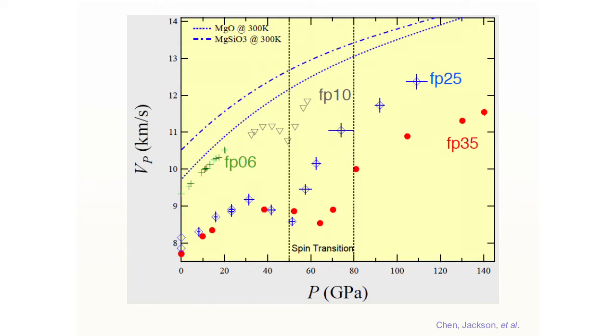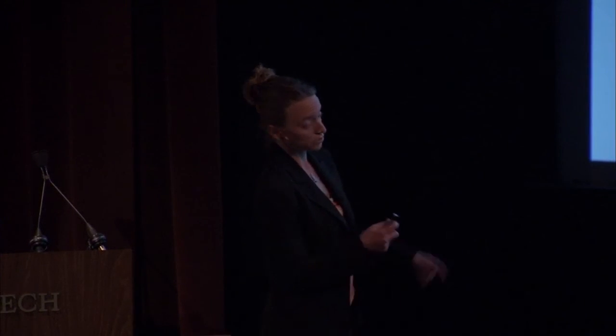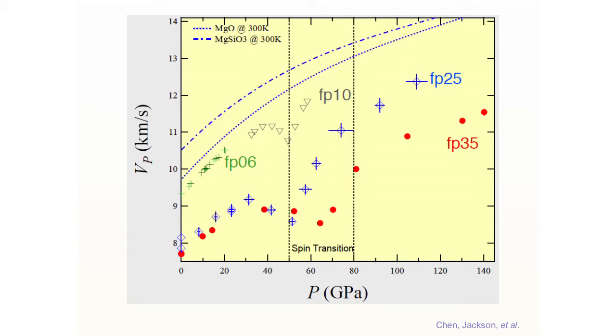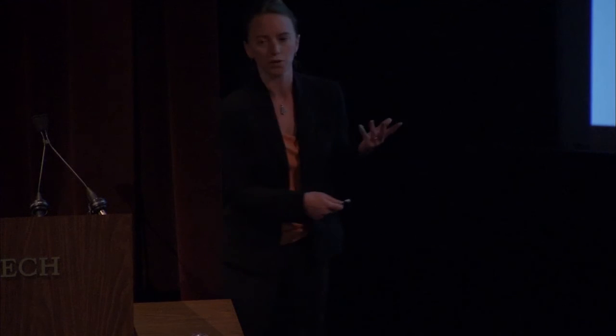And if we measure the wave velocities, we see that they are also anomalous. So if we look at these lines here, that describes normal material, which generally increases with increasing pressure. And this is work that postdoc Bin Chen is working on. But as soon as we add iron into the system, which is indicated by these numbers, or the amount of iron in the oxide, we see that it increases first and then decreases, and then increases again. And this region right here is due to that spin crossover. Those outer D electrons are pairing and causing this behavior that wouldn't have been predicted if we stopped, which had happened about 10 years ago at about 20 or 30 GPa.